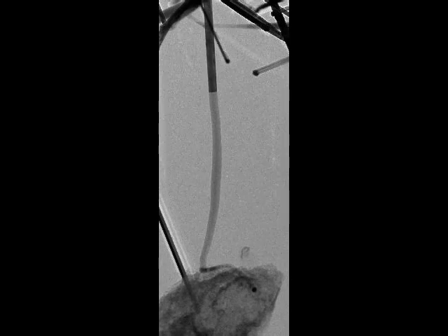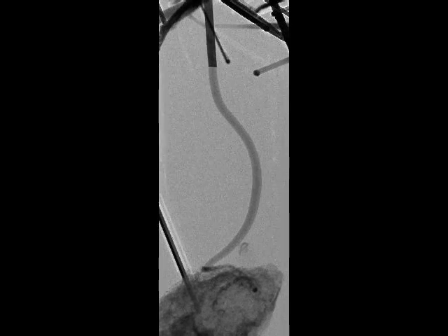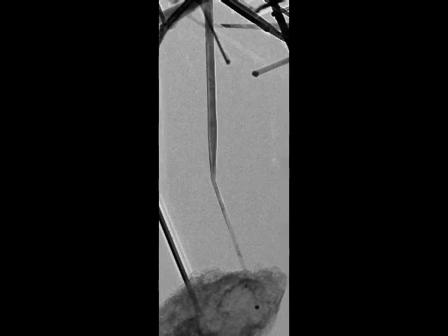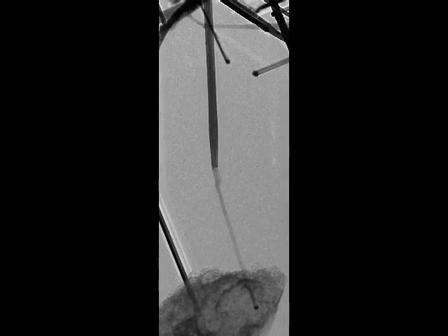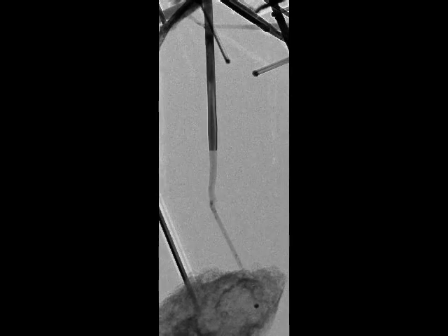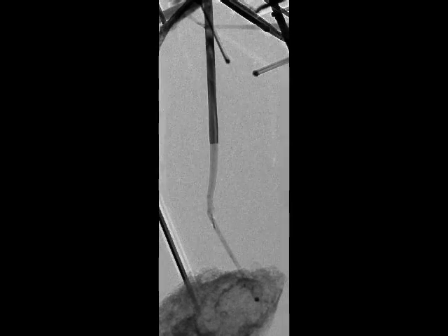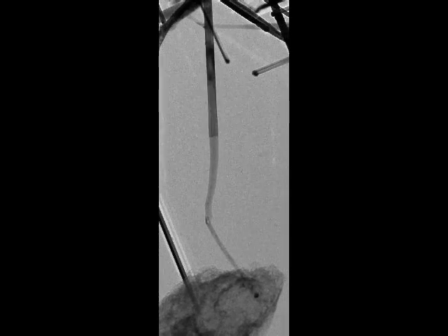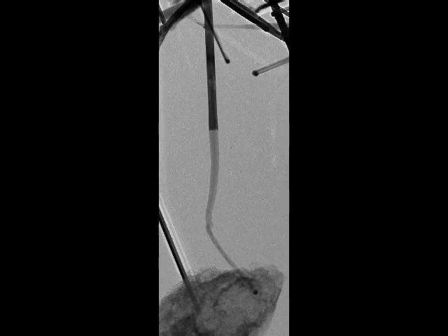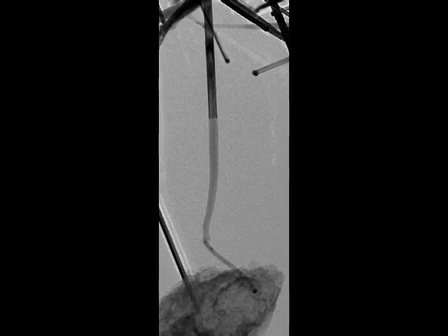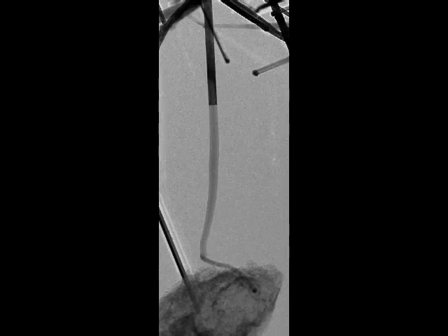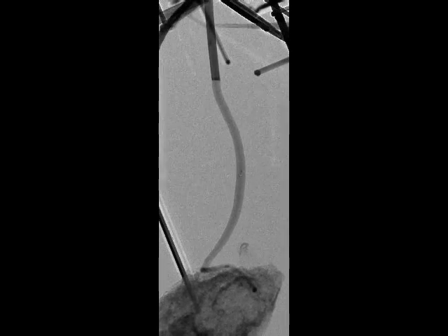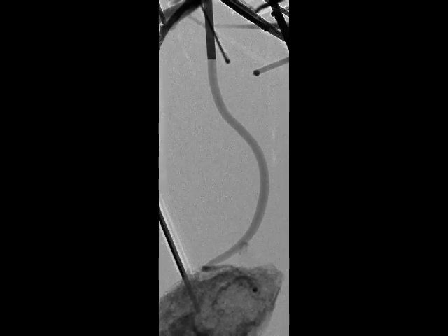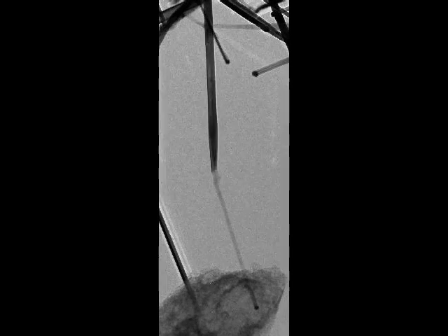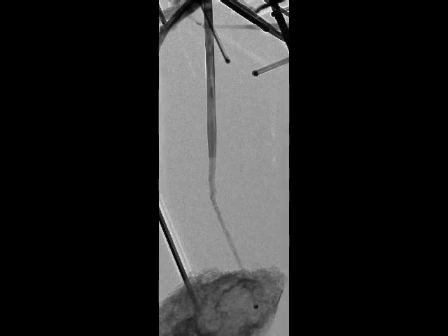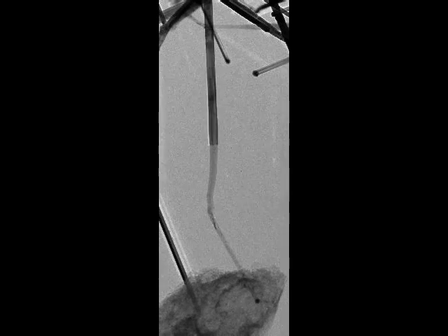If these wires are put in parallel in an electrode material, then we can accommodate a larger number of lithium ions into the electrode material without having to short the two electrodes of the battery together. And more than this, a little bit further, this allows us to think out of the box about ways in which we can store and extract lithium into storage materials by introducing this concept of heterostructuring in the storage material itself.